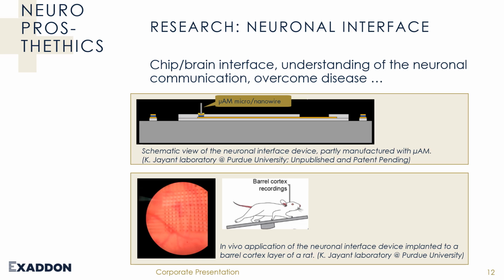So they measure the neuronal activities of the rat by stimulating the rat in different ways. And they're measuring this kind of signals, what happens there. And the device on the top part is, they need nanowires, tiny wires, very precise and with a high aspect ratio. And we are the only company and only method which allows to print wires with a diameter below a micrometer and up to 20 to 50 micrometers long and height. And this is how we use micro additive manufacturing with metal parts for neuroprosthetics applications.